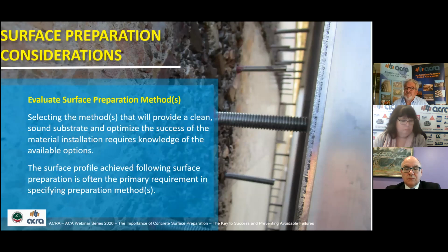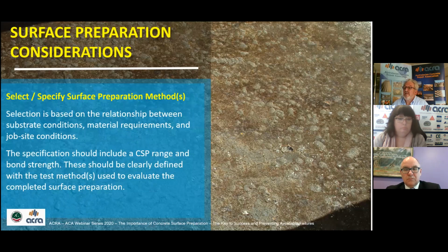Evaluation of surface preparation methods. Selecting a method will provide that clean substrate that we're looking at. It's got to optimise the success of the material installation. It requires knowledge of available options. Profile achieved following surface preparation is the primary requirement. Preparation methods: selecting and specifying the method. Final selections based on the relationship between the substrate condition, material requirement, job site conditions we just looked at. Specification can include a CSP range as well as other criteria, like the strength requirement we mentioned with the substrate. The requirements should be clearly defined in the spec, along with test methods that need to be used to evaluate the preparation.